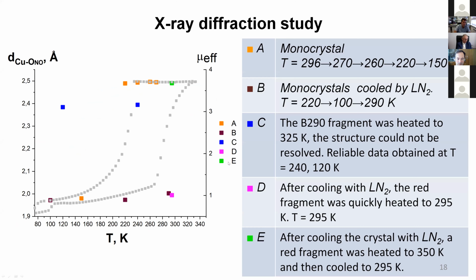To explain the non-trivial magnetic behavior, we made many attempts to study its structure at different temperatures. Gradual decrease in temperature from room temperature to 220 Kelvin does not lead to a significant change in structure, but further cooling to 150 provokes the crystal to crack. Due to the fact that the crystal was coated with a layer of epoxy resin, the fragments remained held in a shape close to the original crystal. This made it possible to resolve the structure.